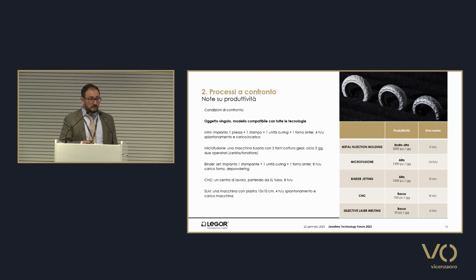In the case of binder jetting, you can carry out a series of printing cycles and have saturation of a furnace, at least with the devices that we have in house, and in the course of one day you can obtain roughly 1,000 items. So in 2 days you can have as many as 2,000 items. This is similar to one complete cycle of sintering. One cycle of sintering is to be carried out after the printing phase.